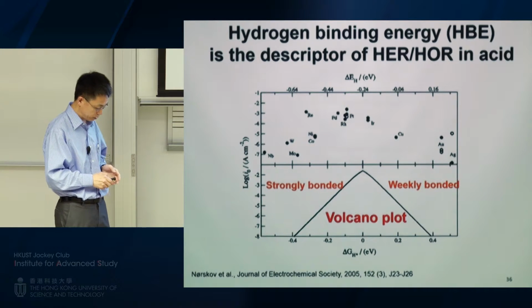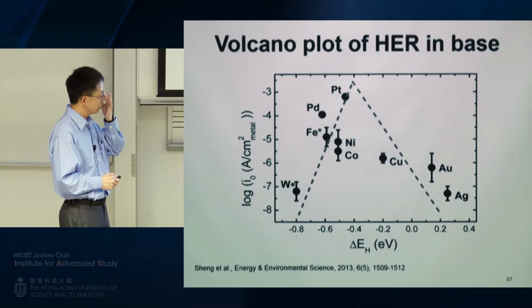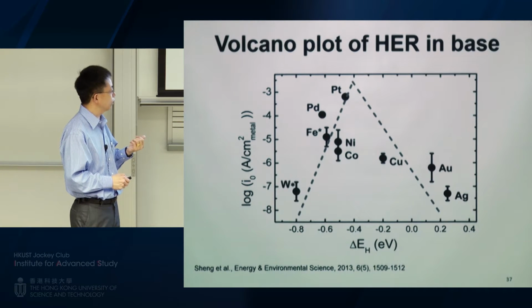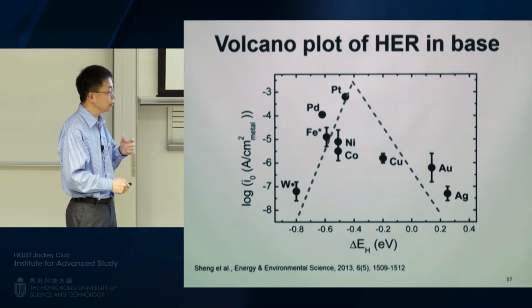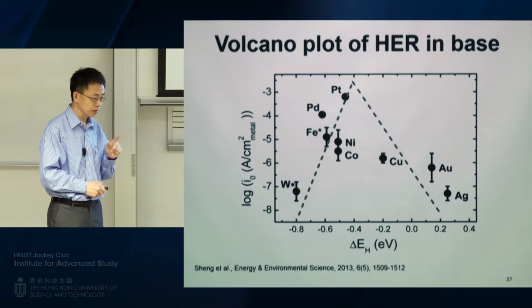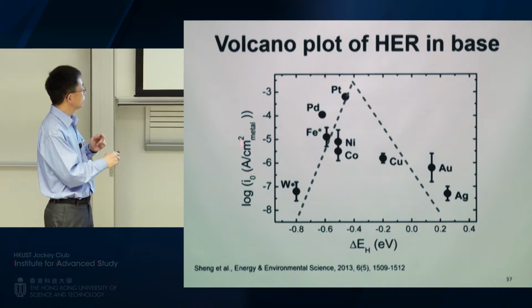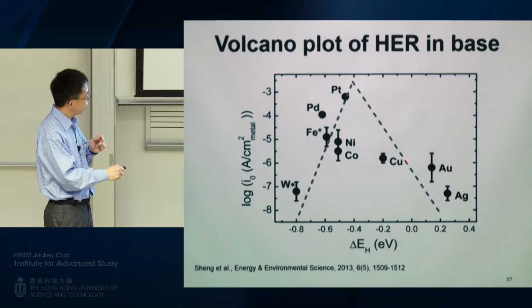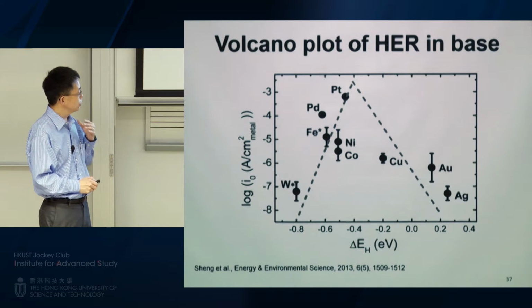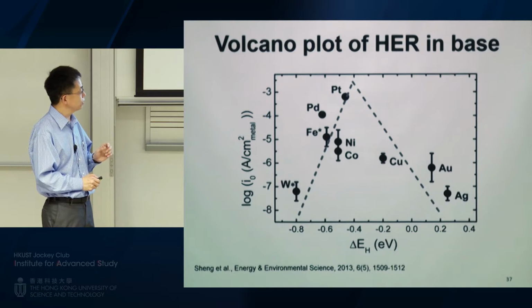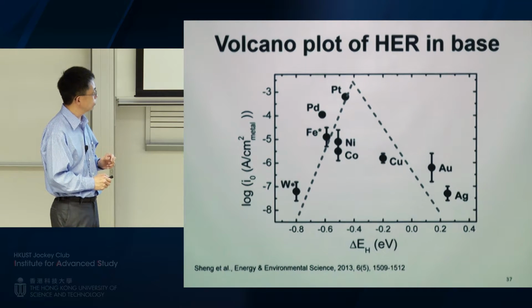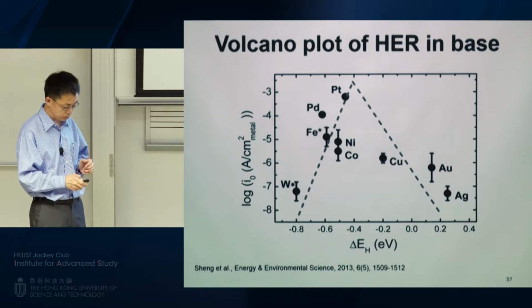So this is important. The first question we asked was, do we have a volcano plot in the base system? So here we also do the DFT calculation. This is actually done in collaboration with Jingguang Chen. He does the DFT calculation. And this vertical axis is the HER exchange current density. These are the metals. So you can see we have roughly a volcano plot as well, and platinum is at the top. So this was good. Hydrogen binding energy appears to be still a very important parameter for deciding the reactivity.